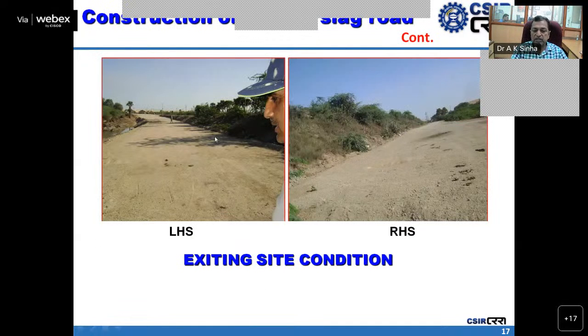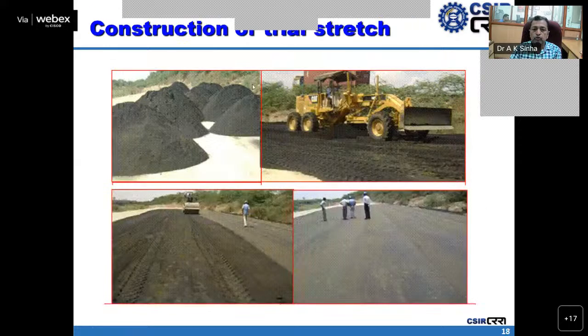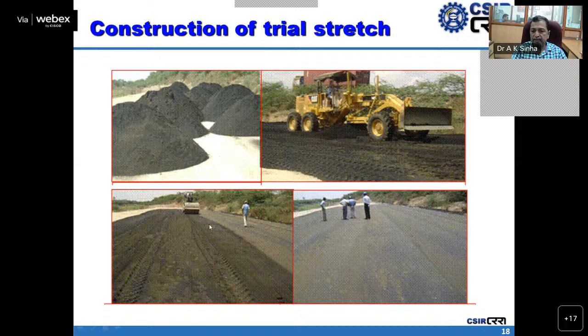This is the existing site condition at the left hand side, and this one is the right hand side, before the construction of the ROB approach road. So this is the copper slag stacked along the proposed alignment, where the existing road was a 2-lane undivided road, and it was proposed to be a 4-lane divided road. In one approach, if you see, copper slag was stacked and then spread and rolled out, and you will see one layer compacted is there.